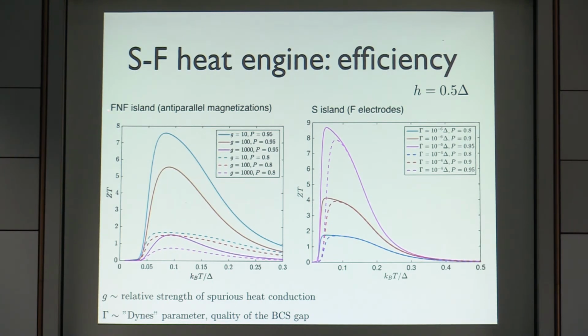So in this case the island is normal, and you get ZT values which can reach, let's say, 7 or 8 in some very optimal case with very high polarization of the interface. In the case of the superconducting island, the electron-phonon coupling is actually weakened by the fact that you have a gap in the dispersion. And in this case, you get even higher ZT values.